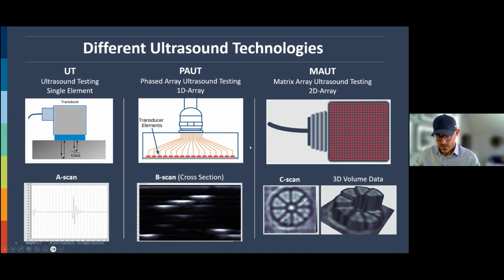Then a few decades ago, in the 60s, 70s, people started using what we call phased array or 1D array. And this was really introduced to the market in the late 90s, maybe early 2000s, where they put a lot of these transducer elements next to each other. So you can imagine this transducer on the left here, you put many of them next to each other. Of course, they're a little bit smaller. And then you get many, many A scans in a row. And if you flip these A scans and put them next to each other here, as in a B scan, this is a B scan of 128 A scans. And then you can say that a high value of the A scan gives you a white color, and a low value gives you a black color. And then all of a sudden you have a cross section. So this is easier to interpret. It's a slice through material, and you can easily see where the cracks are and so on.